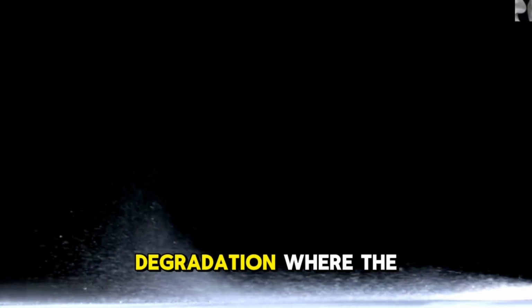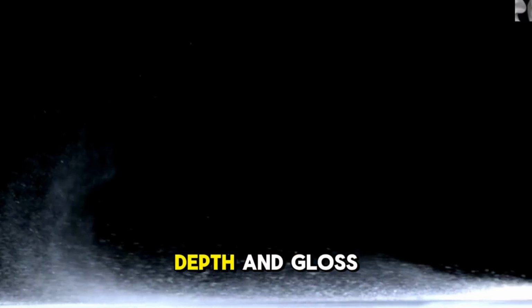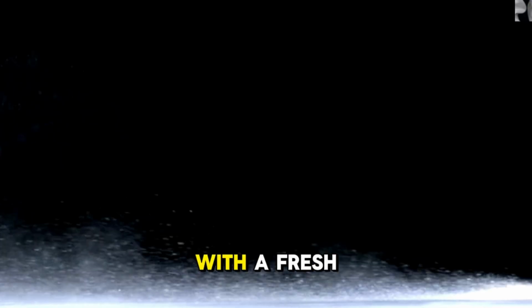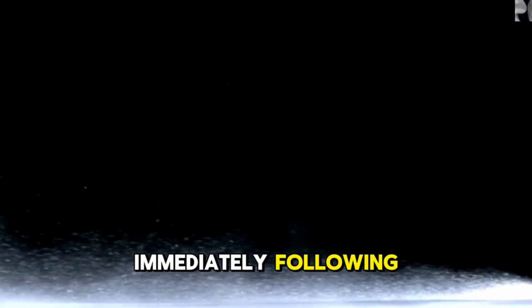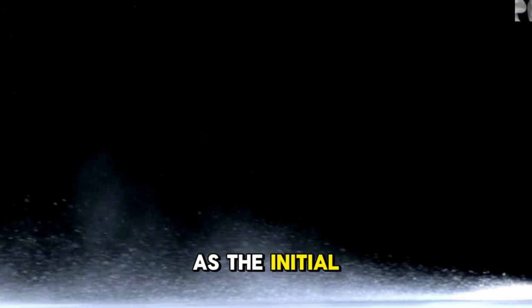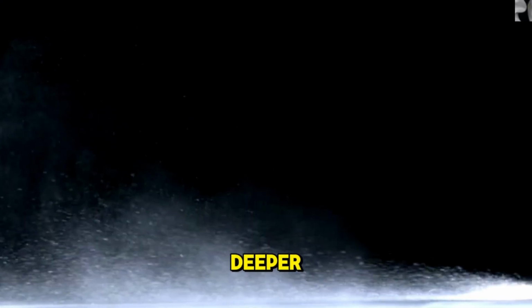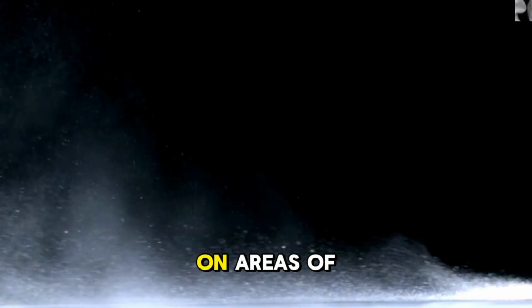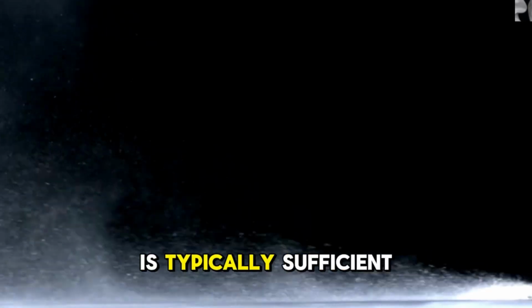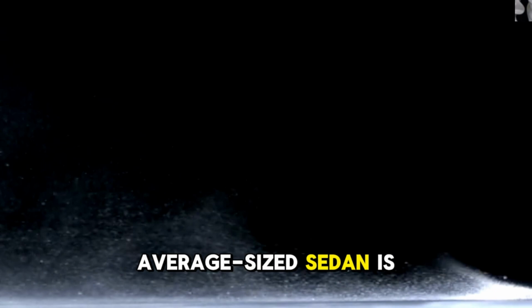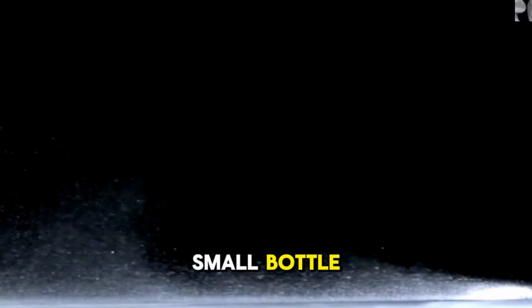technique across all surfaces. On areas of severe degradation where the paint has lost the most color depth and gloss, a second pass with a fresh application of solution immediately following the first is beneficial, as the initial application may not have fully saturated the deeper fracture network in those areas. On areas of lighter weathering, a single pass is typically sufficient. The total material consumption for an average-sized sedan is well within the capacity of a single small bottle. The application process for a complete vehicle, working at a careful and unhurried pace, takes between 60 and 90 minutes.